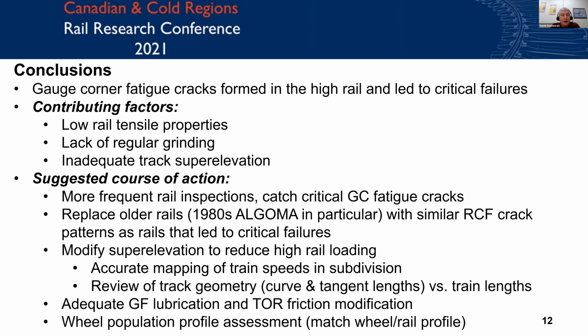There was a lack of regular grinding, and there was inadequate track super elevation, which caused more damage on the high rail. Some of the suggested course of action here would be to simply do more frequent inspections to make sure that the cracks that we saw during the track walk don't lead to any type of damage, or if you have a broken rail, replace it. The next best is obviously the rail replacement. This rail is fairly damaged. Grinding will not solve those types of cracks, will not remove them at this point.